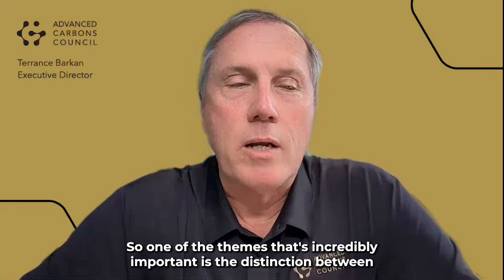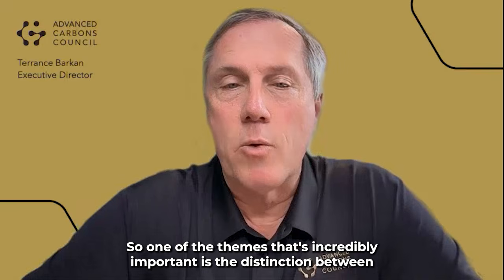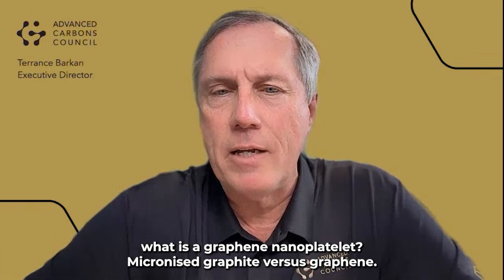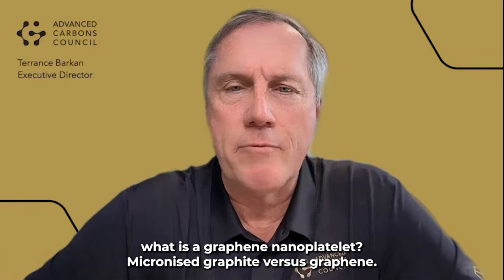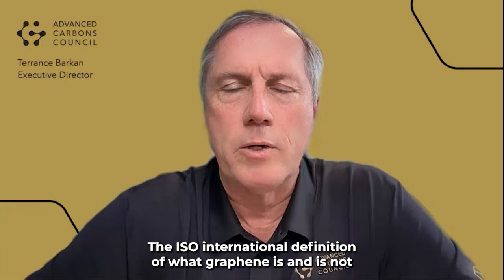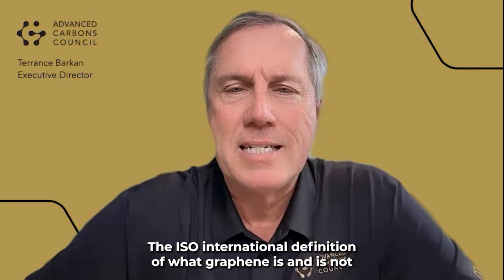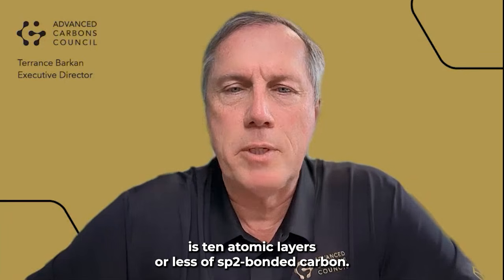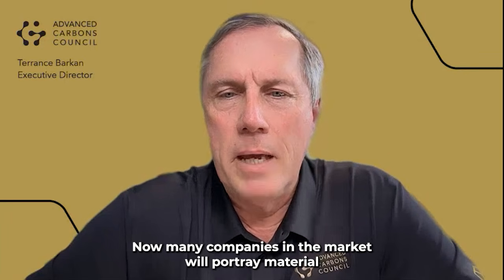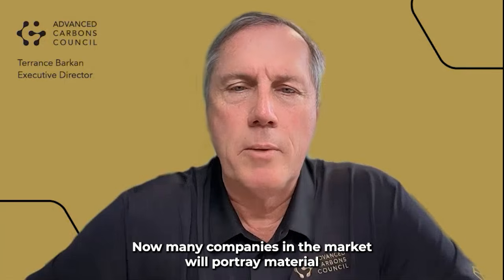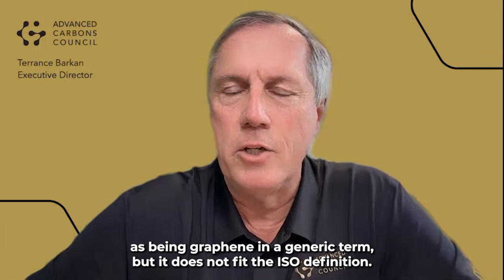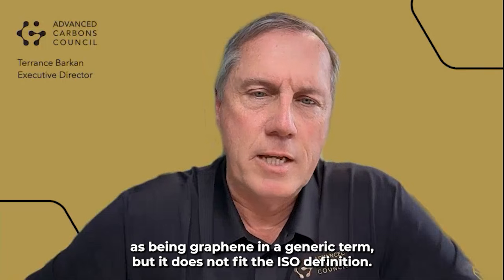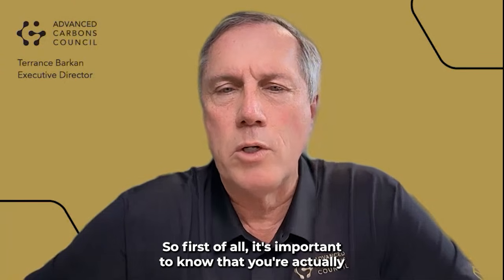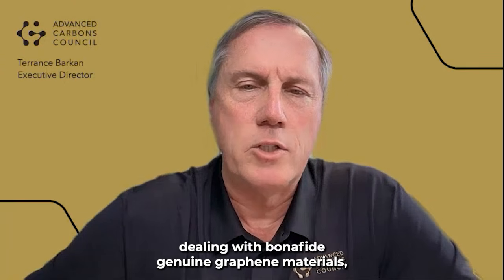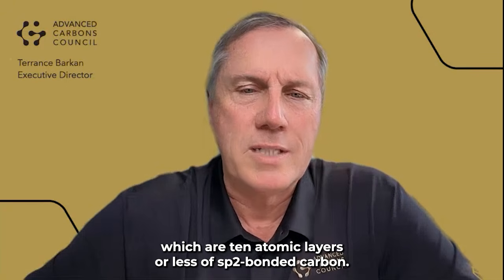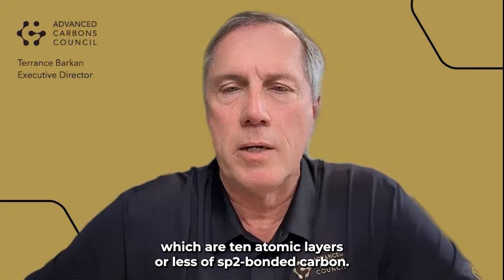So one of the themes that's incredibly important is the distinction between what is a graphene nanoplatelet, micronized graphite, versus graphene. The ISO definition, the international definition of what graphene is and is not, is 10 atomic layers or less of sp2 bonded carbon. Now, many companies in the market will portray material as being graphene in a generic term, but it does not fit the ISO definition. So first of all, it's important to know that you're actually dealing with bona fide, genuine graphene materials, which are 10 atomic layers or less of sp2 bonded carbon.